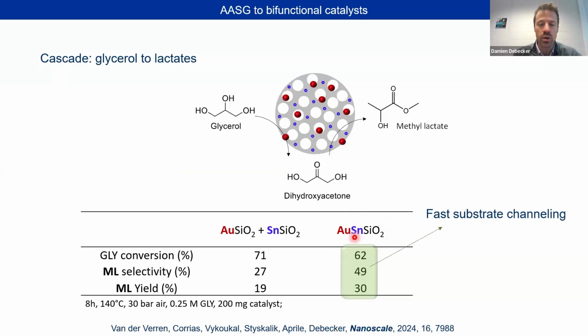this catalyst, so when we compare the mechanical mixture and the bifunctional catalyst, of course, the amount of tin and gold in both cases is exactly the same, but it's just that here they are on the same particles. You see the selectivity that increases significantly. For this kind of reaction, 50% is already something that is quite remarkable. And it is because we have a fast substrate channeling from one active site to the other active sites here.